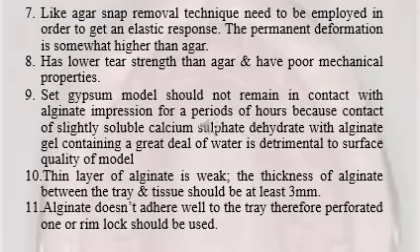7. Like agar, a snap removal technique needs to be employed in order to get an elastic response. The permanent deformation is somewhat higher than agar. 8. It has lower tear strength than agar and poor mechanical properties. 9. Set gypsum model should not remain in contact with the alginate impression for a period of hours, because contact of the slightly soluble calcium sulfate dihydrate with the alginate gel containing a great deal of water is detrimental to the surface quality of the model.